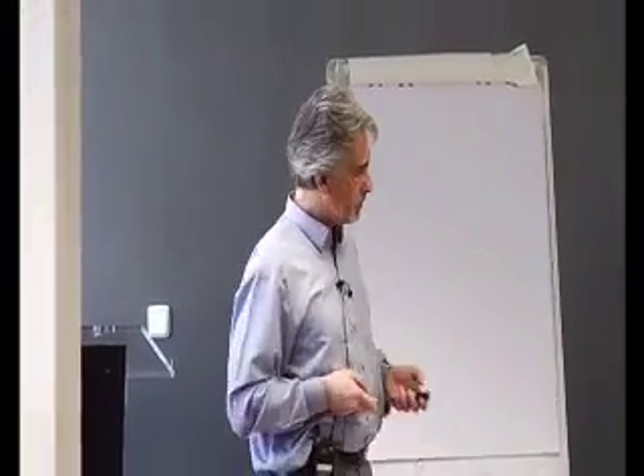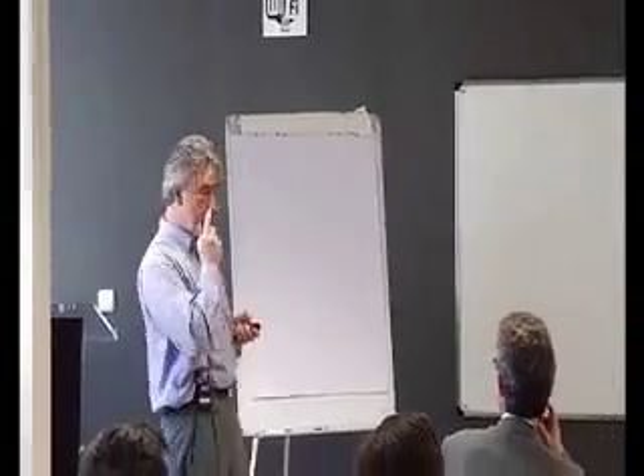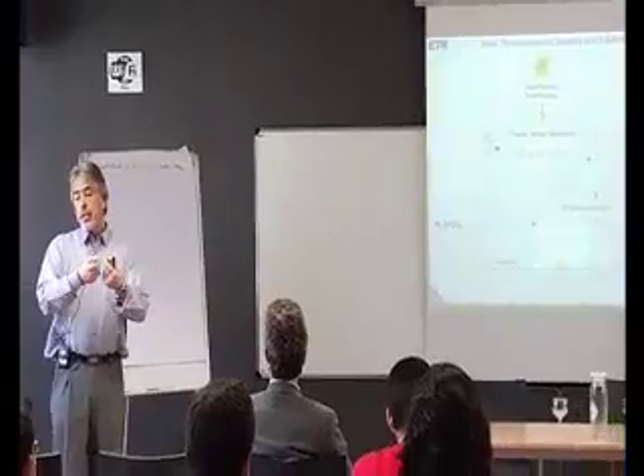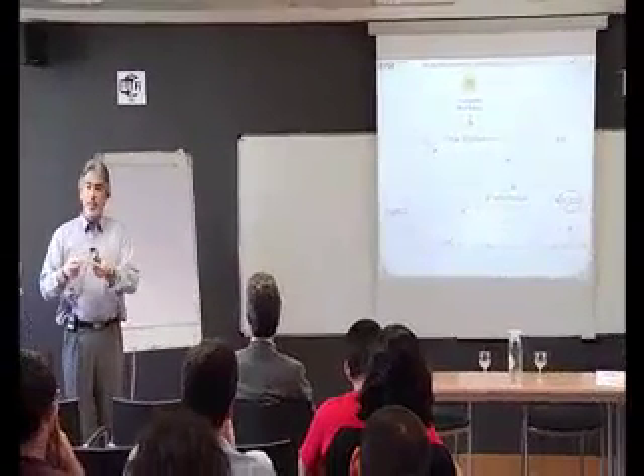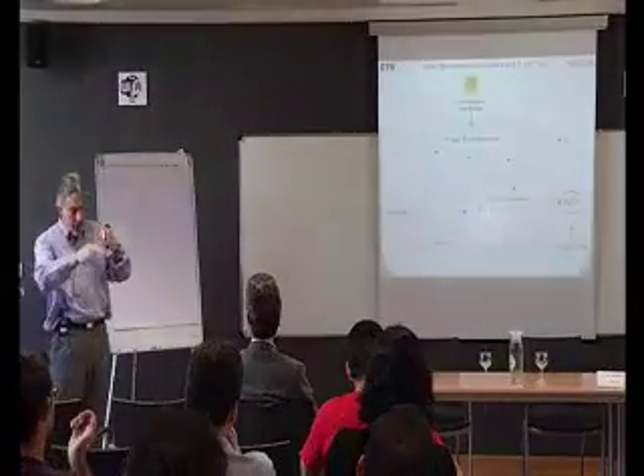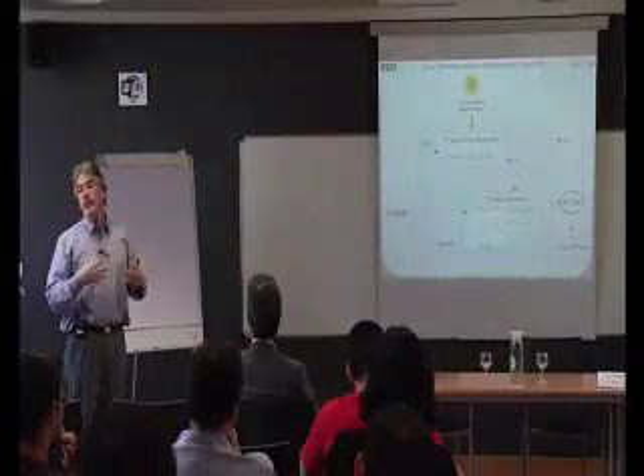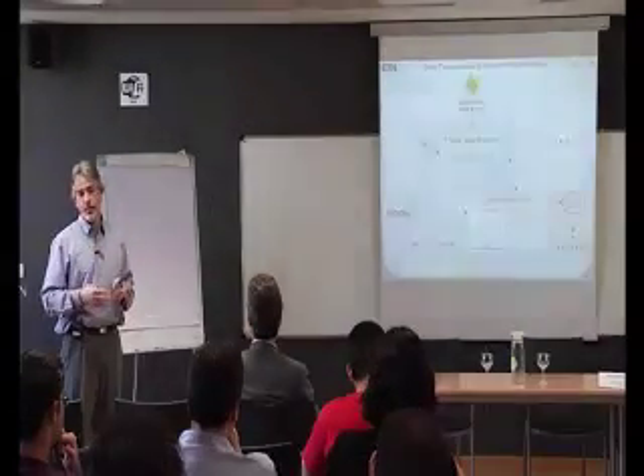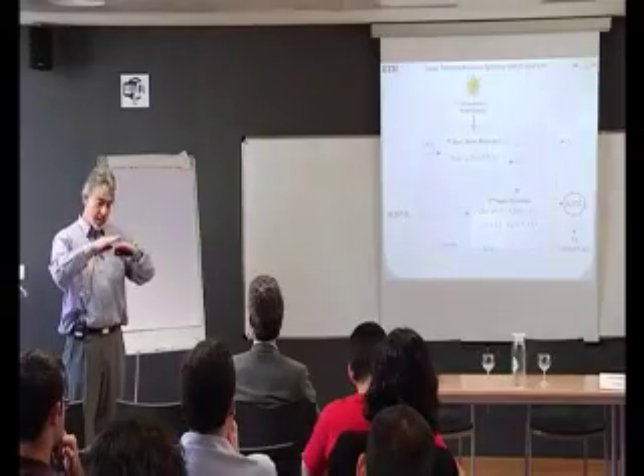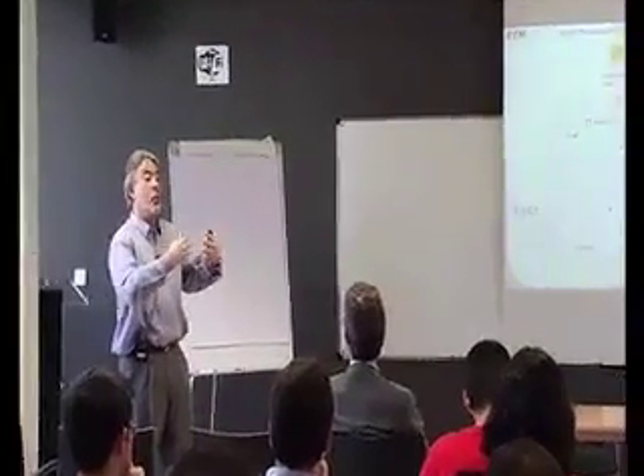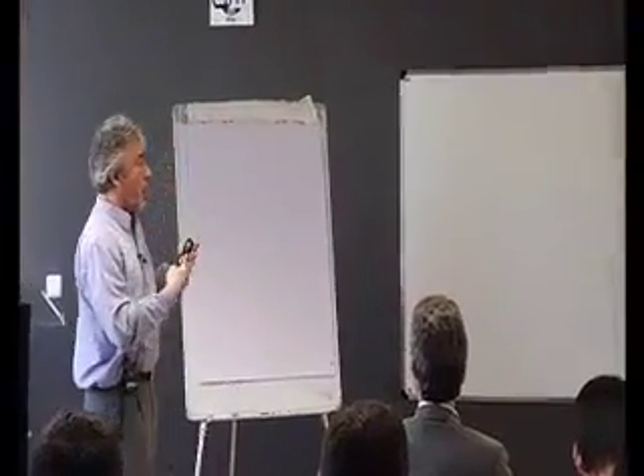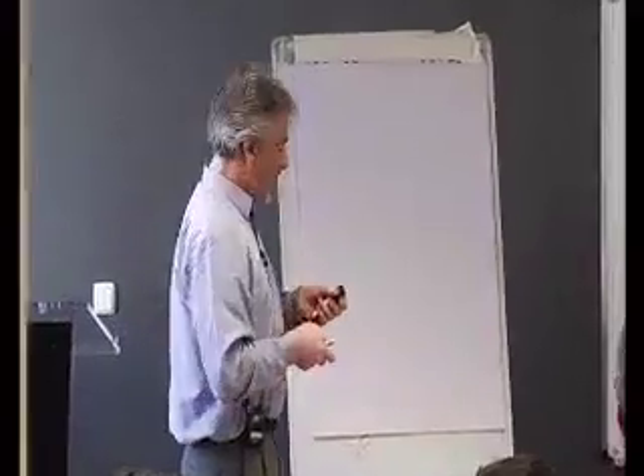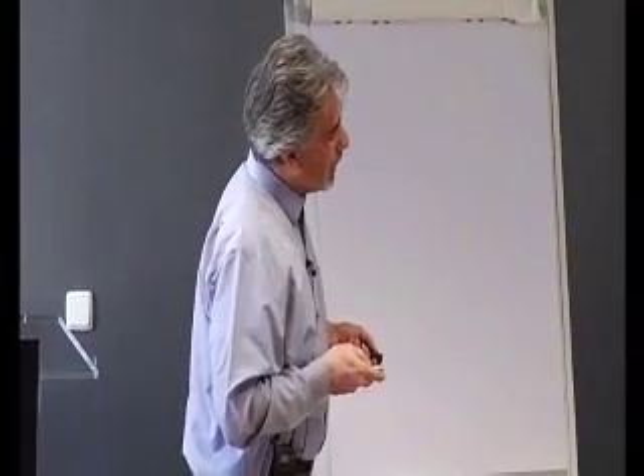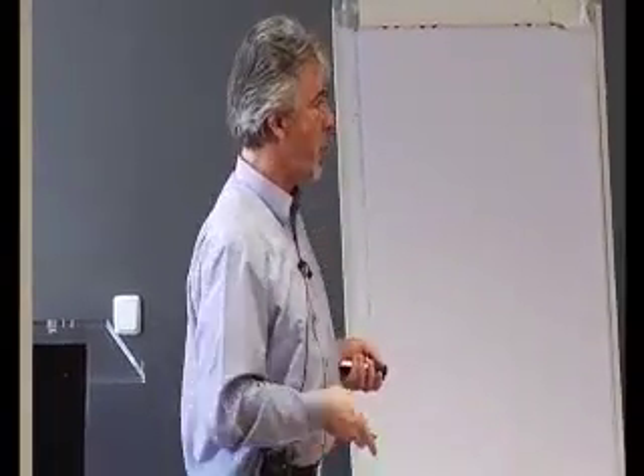Let me now come to the second step: zinc reacting with water and CO2. It is well known that when you expose a zinc particle to either water or CO2, it reacts very fast, but right away it creates a layer around the particle that stops further reaction. You see that as well, for example, in aluminum. Aluminum reacts very fast, but it creates a thin layer of aluminum oxide, and then oxidation stops. In order to overcome this problem, we decided to work with nanoparticles, of a size that is comparable to this layer of zinc oxide that forms when it's exposed to the reacting gases.